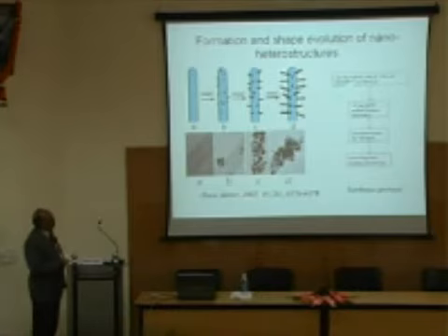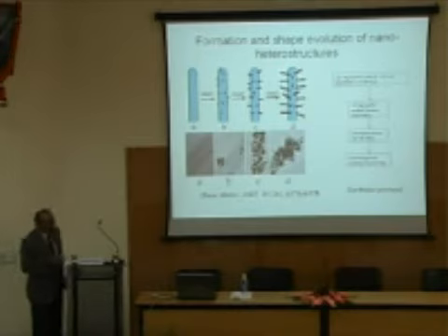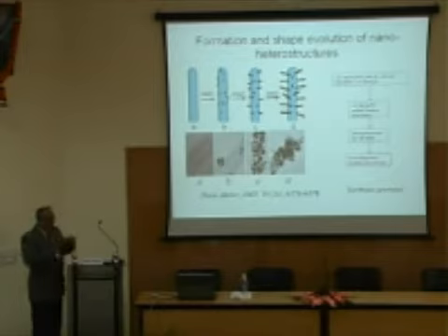And you add some formic acid and water, and what you start getting is platinum particles on top of the carbon nanotubes. As you continue the reaction, you can study it under a high resolution transmission electron microscope, and the particles will grow.